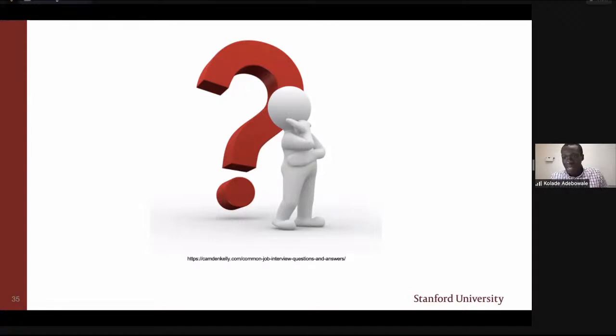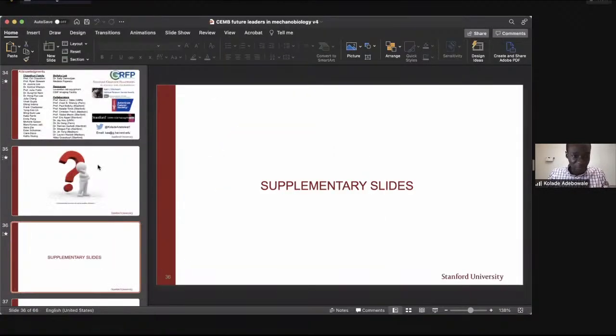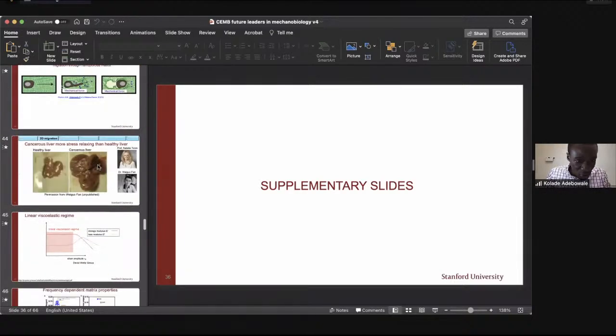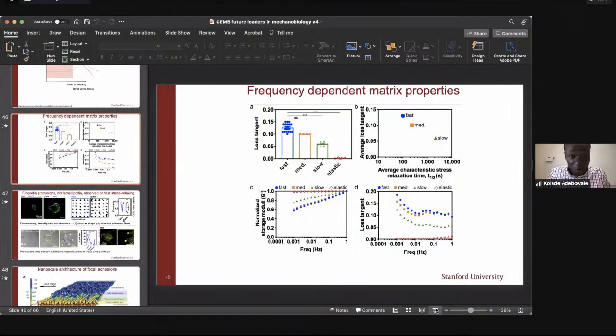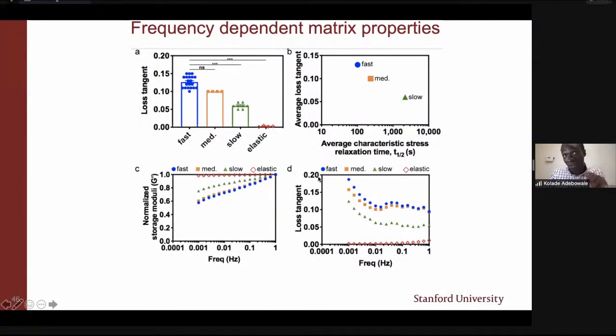It's frequency dependent. Yeah, that is a very good point. We have not looked at that specifically for that material system, but I will show some backup slides. In the first part of the talk, we used an alginate Matrigel system. And as you mentioned, if you look at the data in panel D on this slide, in the bottom right, we definitely see, looking at the loss tangent as a function of frequency, that there is a frequency response. We have not done these kinds of extensive characterizations for the material in the second part of the talk, but we certainly anticipate that there will be a frequency dependent response in the loss tangent as well. So it does matter what the frequency is. Thank you. Yep.